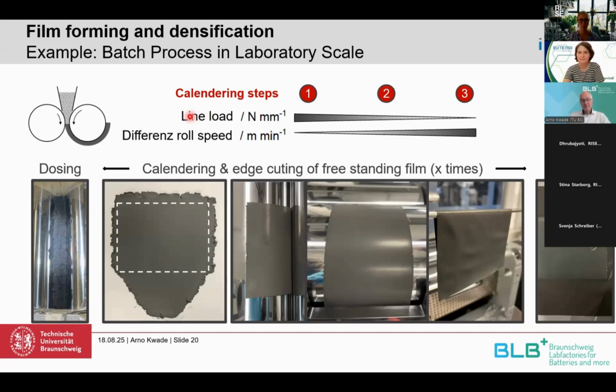If we do that in a more discontinuous way, you can see it here. For example, by increasing or decreasing the line load from the first to the last step, but increasing the differential speed of the rollers, you get thinner films. And at the end, it really looks like a thick piece of paper, which you can then nicely laminate on the substrate.